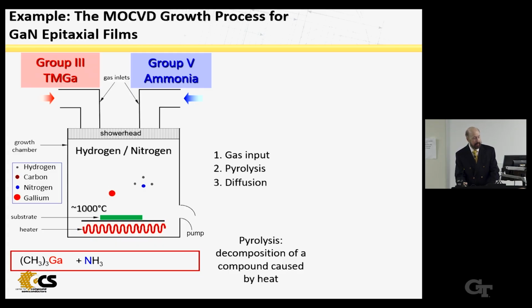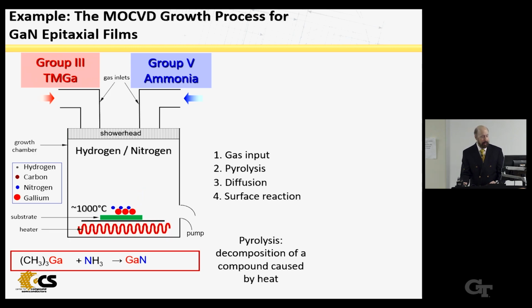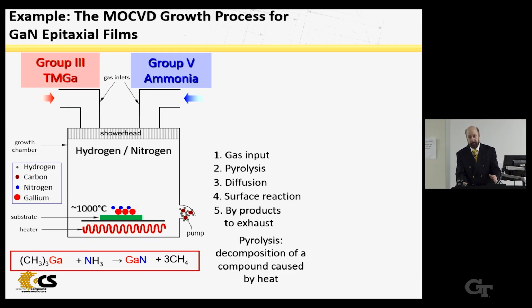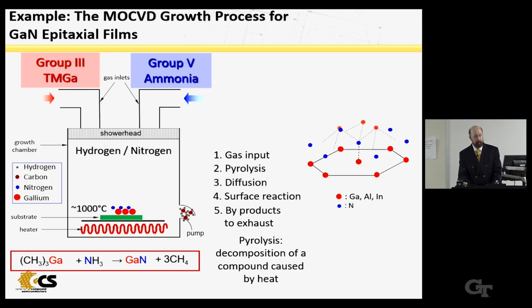And those react again on the surface to form a thin layer by diffusion and then a surface reaction, forming gallium nitride and 3 moles of methane as a byproduct. Methane is stable at this temperature, so it's just swept out by the main carrier gas flow into the pumps. So using this process, we can build up a crystal layer by layer.